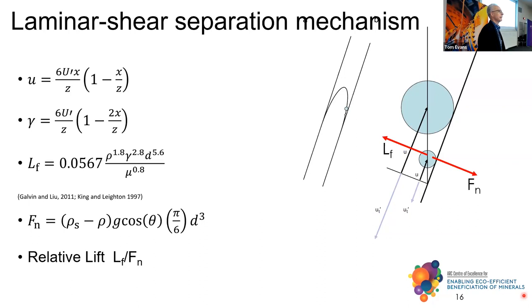The sum total of that theory: you've got a velocity field, which is very simple — it's a parabola. You differentiate that and you get a shear rate. We've got a lift force directly out of the work of King and Leighton, adapted to our geometry, operating in the normal direction to the incline. It competes with the weight force in the normal direction, fn. You can also see in the schematic that the positioning of a large particle is more into the flow and therefore exposed to higher velocities than a smaller particle, which also diminishes the effects of particle size.